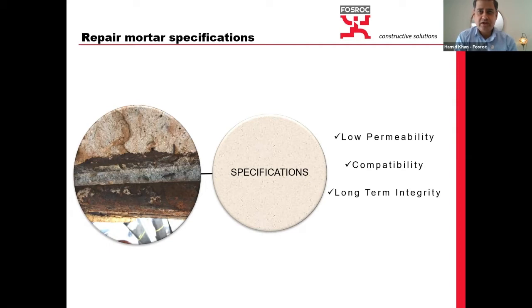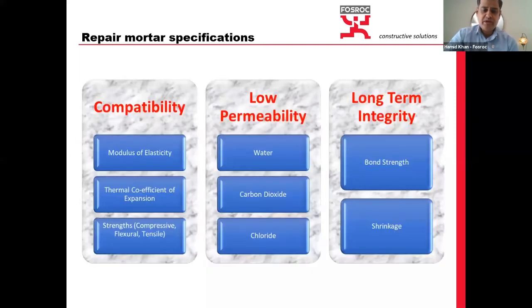When we talk about concrete repairs, when we are repairing the structural element like columns and beams, that structural repair is a bit different than the concrete repair mortars which are used for protection or just to fill the pinholes, for example, or blowholes, or just to protect the top surface against the ingress of chlorides or carbon dioxide. So it's very important to know that the repair mortars should be low in permeability, they should be compatible, and they should have long-term integrity. What do we mean by these three terms? When I say that in order to ensure the durability of repaired areas, the cementitious repair mortars must exhibit low permeability, low shrinkage, and compatibility with the substrate.